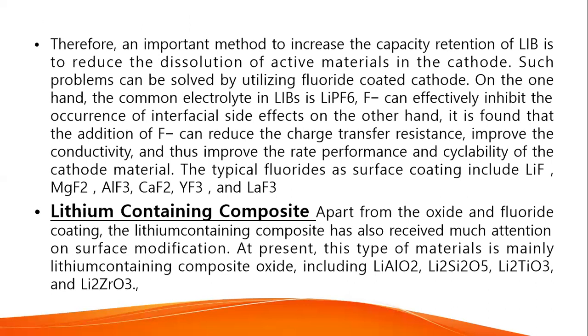fluoride-coated cathode. On the one hand, the common electrolyte in LIBs is LiPF6, and F- can effectively inhibit the occurrence of interfacial side reactions. On the other hand, it is found that the addition of F- can reduce the charge transfer resistance, improve the conductivity, and thus improve the rate performance and cyclability of the cathode material. The typical fluorides as surface coating include LiF, MgF2, AlF3, CaF2, YF3, and LaF3.